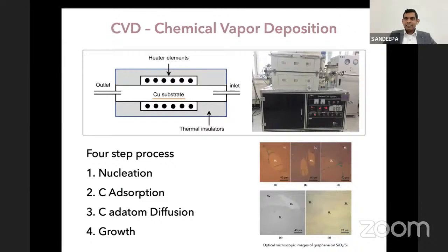If I give an introduction to CVD graphene, this is one of the most interesting techniques in the world today. In CVD techniques, we use CH4, sometimes C2H2. These gases, we let them atomize at very high temperature, like 1000 degrees. And we use a substrate. Generally, we use copper, sometimes nickel. Nickel is good for multi-layer graphene. Copper is very good as a catalyst substrate for single-layer graphene.